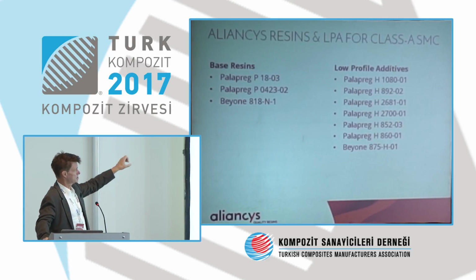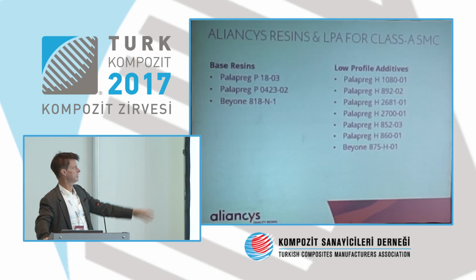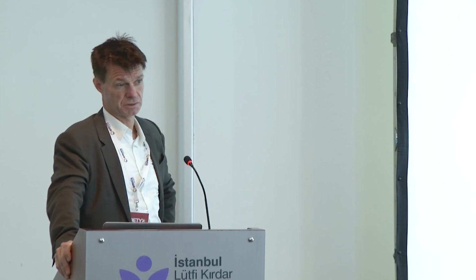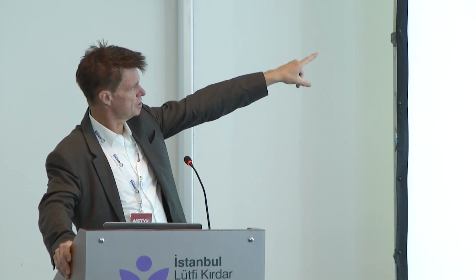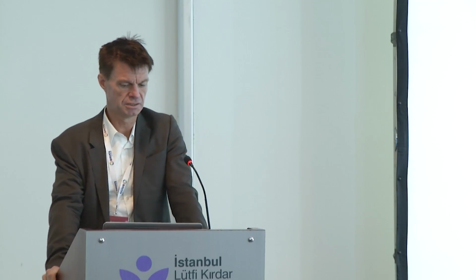So, but these products, they have a shrinkage, and you need to compensate. And the compensation can only be done by adding an LPA, low profile additives, that are typically used, especially for Class A, premium surface. These are the following. So you see here Palapreg H 1080, it's a PVAC solution.